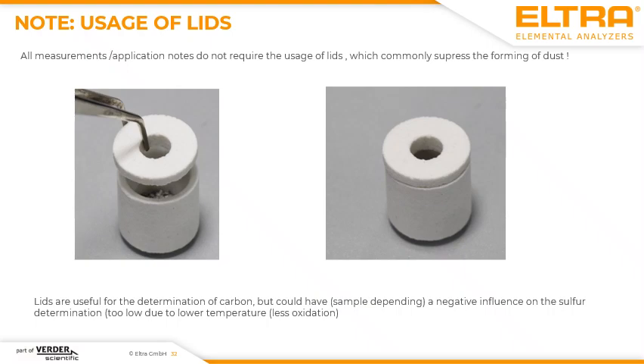For me, it's important to provide some more information about other typical helping tools for correct analysis of finely divided powders, which means you can apply a lid on the sample. For example, these kinds of lids, which can also be purchased from ELTRA, are a good helping tool when you would like to measure carbon content in a very narrow range. But depending on your sample composition, it could be that this kind of tool could falsify the results of sulfur. This is due to the fact that, for example, the lance, which puts the oxygen stream directly on the sample, is maybe blocked a little bit. And this means that the resulting temperature in your sample could be a little bit reduced.